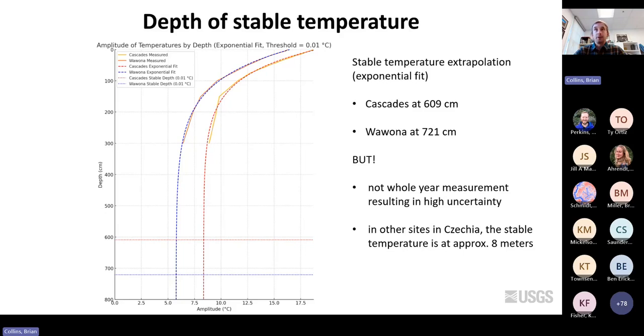But now the extrapolation, the exponential fit shows that in the south-facing slope, the stable temperature is at about 6 meters, and in the Wawona, it's more than 7 meters. This coincides with the other sites we monitor in Czech Republic or in Italy, where we usually have the stable temperature at around 8 meters. But to confirm this, it will certainly change when we have the whole year record. So from this, you can see that the thermal behavior just 1 kilometer or 1.5 kilometers apart, on the other side of the valley, is completely different.